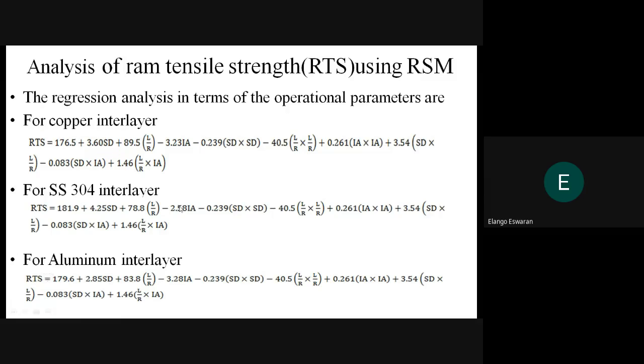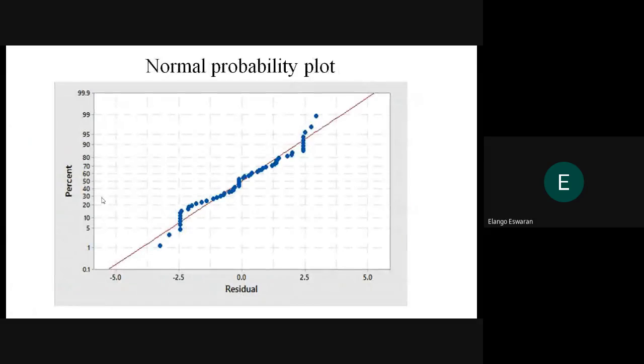The regression analysis of the operation parameters for copper SS 304 aluminum interlayer is shown in this figure. The normal probability plot shows that the residuals of the tensile strength fall near the straight line, and the normal distribution of the error is inferred. Hence, it is concluded that the developed regression model is in agreement with the experimental value.